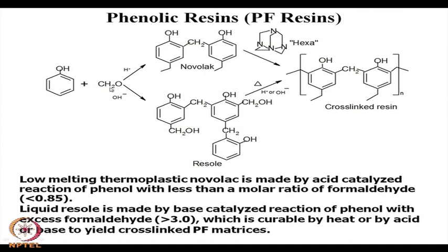1:1 of formaldehyde. Now, this formaldehyde can be considered as a condensing agent as well as a cross linker for this kind of resin system. Here, if the quantity of this formaldehyde is kept less, say 1 mole reacts with less than 1 mole of this formaldehyde, the resin formed will be available in the form of linear molecule, which will remain as thermoplastic, and that grade is known as Novolac resin.